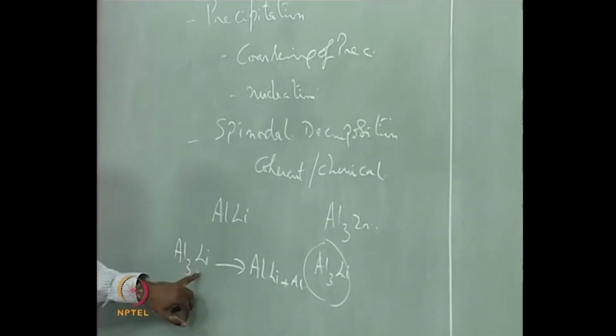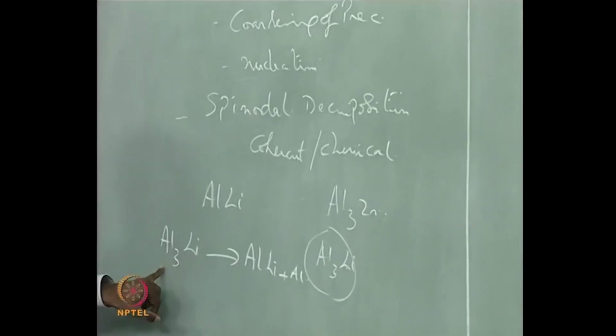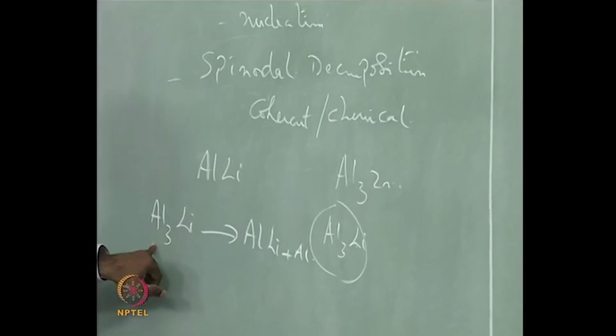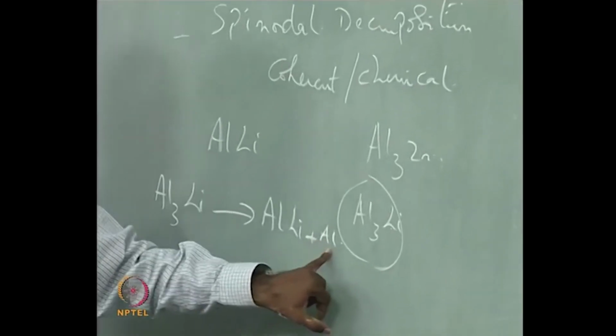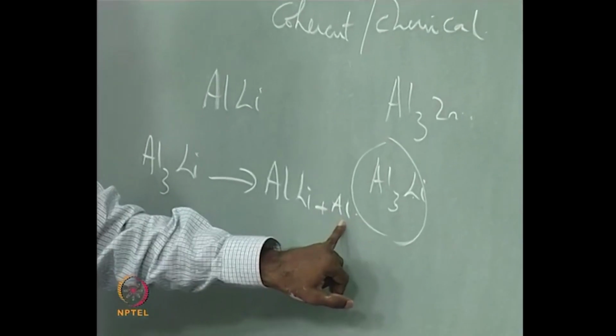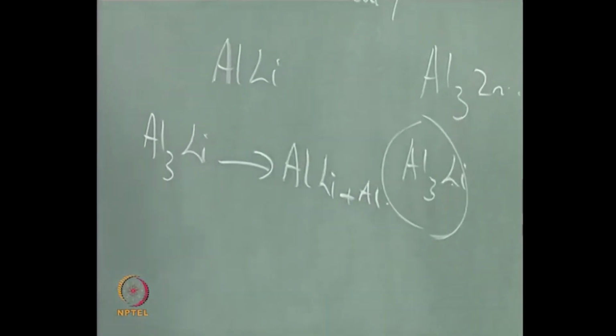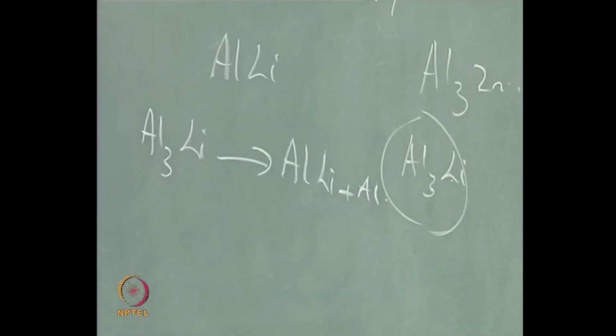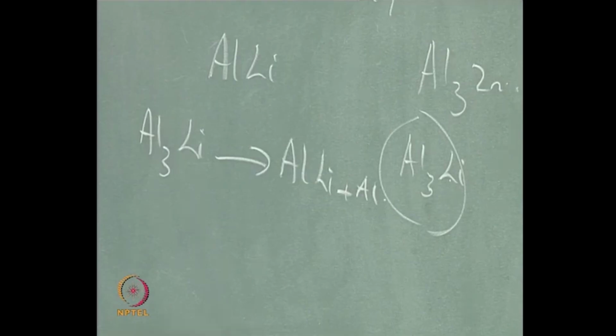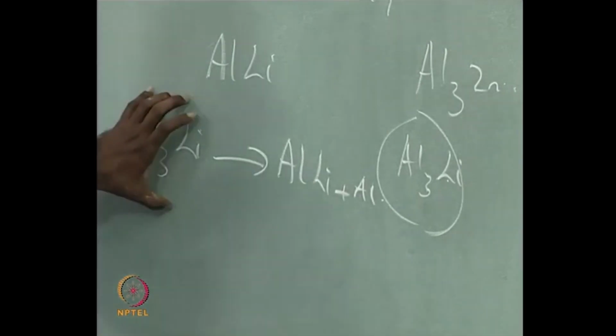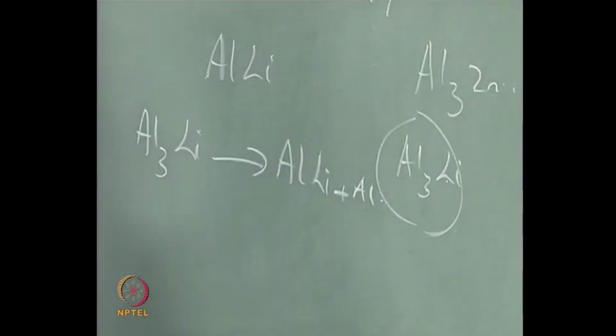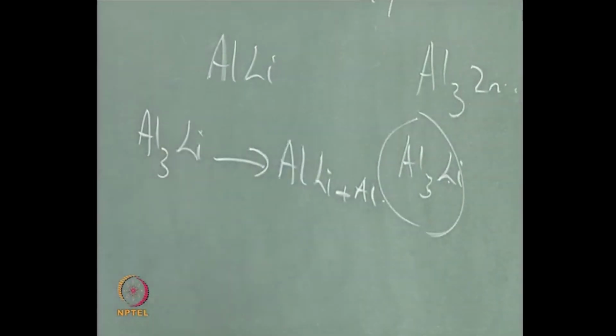So obviously you can see for every lithium atom there are 3 aluminum atoms. So 2 extra aluminum atoms are there. So that 2 extra aluminum atoms will come out. This is something like Fe3C splitting into iron and carbon at higher temperature. So similarly this can happen at high temperature. That means this is not really a stable phase. Whereas this is a very stable phase.